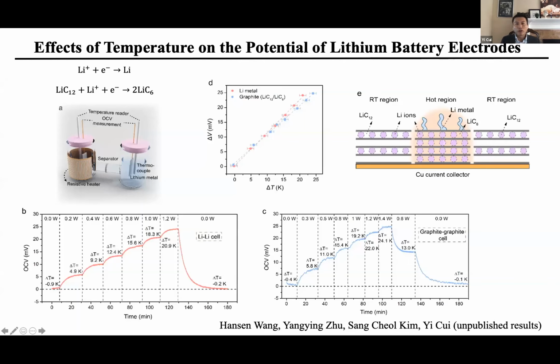Imagine you have a battery cell electrode, and there's a temperature inhomogeneity in there. This is for graphite. In the middle right here is higher temperature. Its potential for lithium plating will go up with temperature. Once it goes up to a potential even higher than the room temperature region of the graphite intercalation potential, you indeed will have lithium plating already happening in the hot region. Even though in the full cell you're thinking your graphite has not gone down to the voltage to plate yet for room temperature, for the local higher temperature spot you already exceed the lithium plating potential, so the plating will happen.